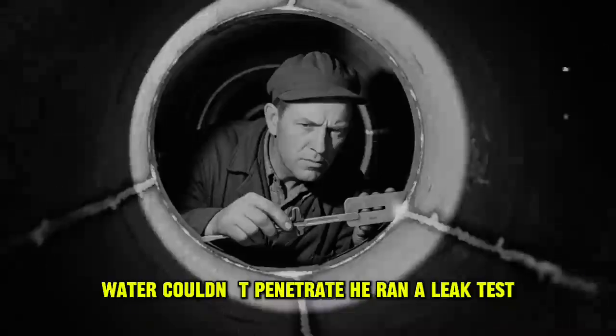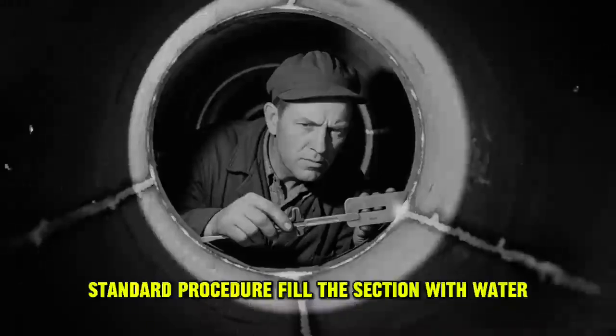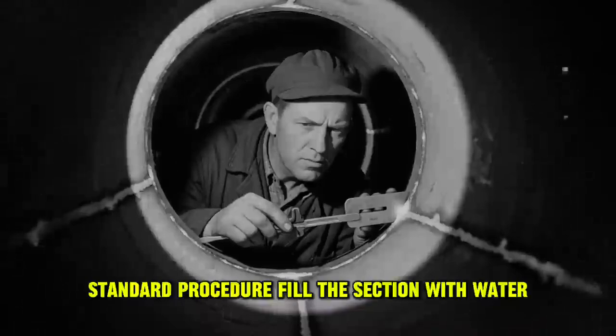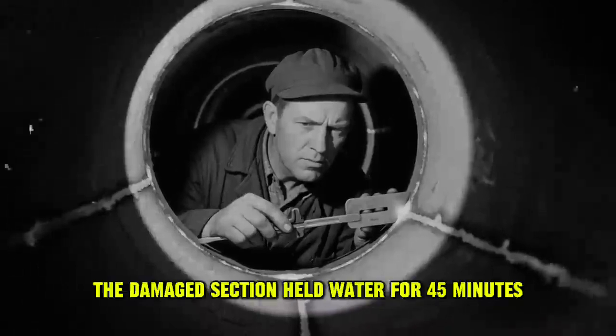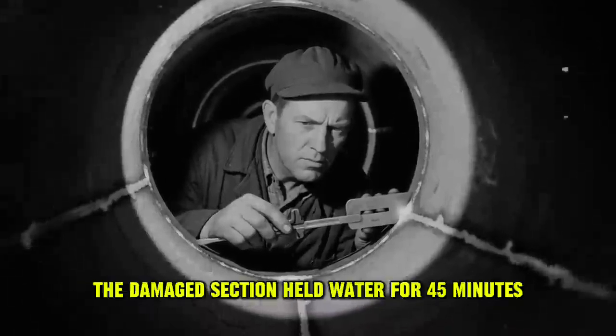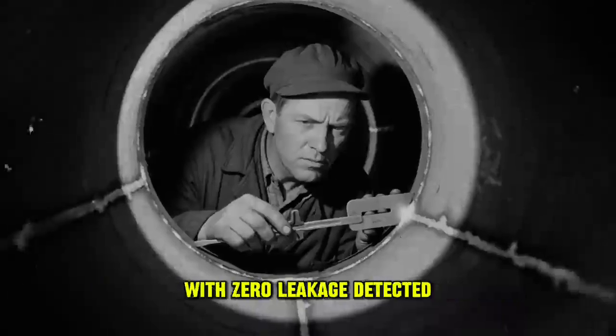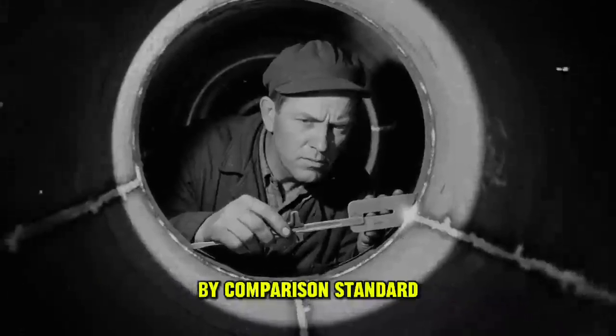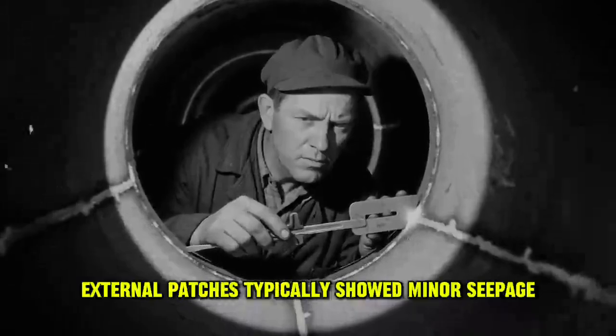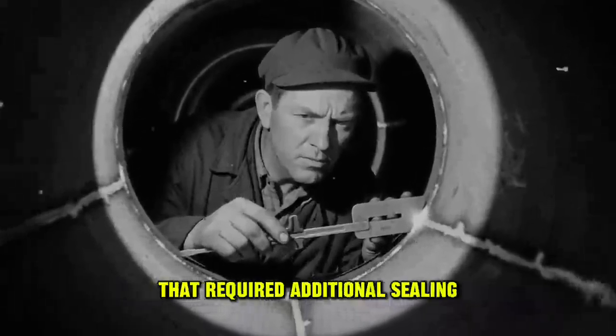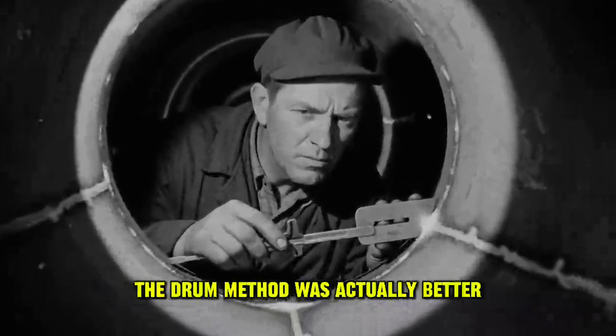Water couldn't penetrate. He ran a leak test. Standard procedure. Fill the section with water. Check for seepage. The damaged section held water for 45 minutes with 0 leakage detected. By comparison, standard external patches typically showed minor seepage that required additional sealing. The drum method was actually better.